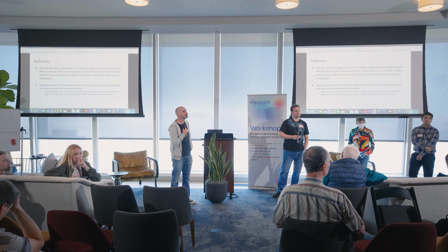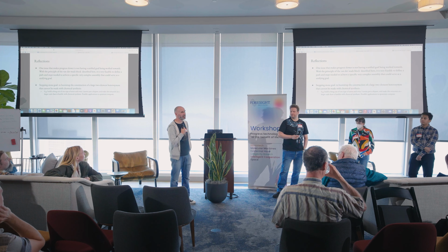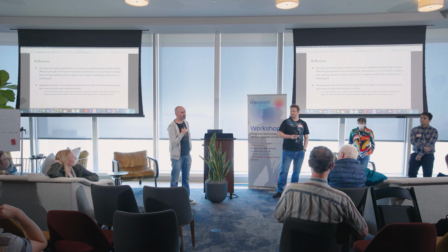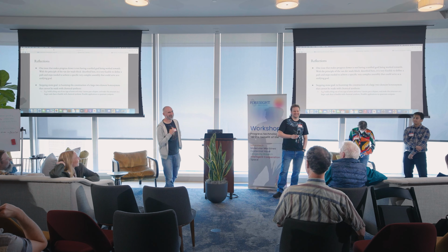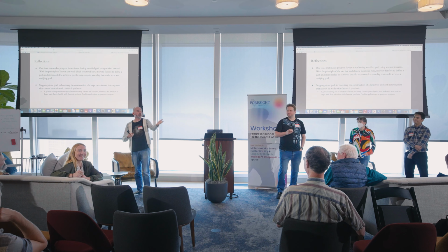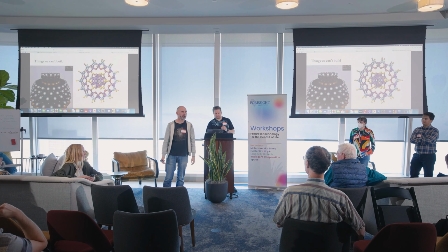I have more of a fundamental question because I'm not very familiar with the field. What happens after you're able to form these structures atomically precise, if they are just held together by van der Waals interactions or other type? How do you make sure that they just don't collapse? Absolutely. That's a great question. If you've got something that's just kinetically limited, and you heat it up, it gets the energy to get out of that. That's a very good question. So that's why I work at 4 Kelvin all the time. Indeed, all those beautiful Crommie experiments where you form the quantum corrals that we've all seen, heat that surface up to 20K and that falls apart.